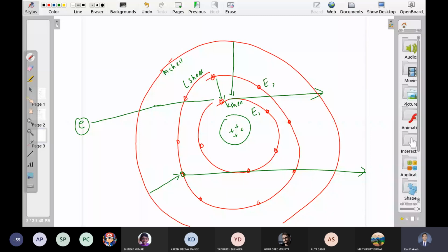These have E3. So when they come back, I mean when they come to a lower energy shell, obviously they will have to radiate their energy. So how much is this energy? This energy appears as X-rays. How much energy is it? E2, the higher level energy, minus E1.